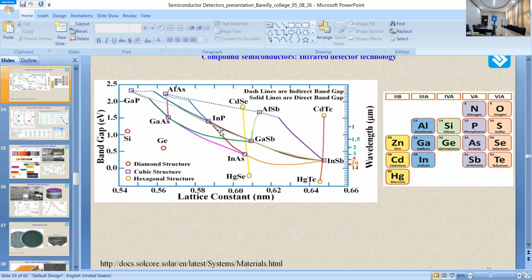Similarly, an indium phosphide substrate is commercially available. If I incorporate a small amount of indium into gallium arsenide, I can make a ternary like indium gallium arsenide, and it should be lattice matched to indium phosphide for proper, defect-free growth. By choosing different compositions of indium, I can cover different parts of the wavelength. To cover from 1.1 micron to 2 micron, I can use indium gallium arsenide on an indium phosphide substrate. In this way I can use different combinations of compound semiconductors, ternary and even quaternary, on compound semiconductor substrates to make different kinds of near infrared, short wave infrared, and long wave infrared detectors.